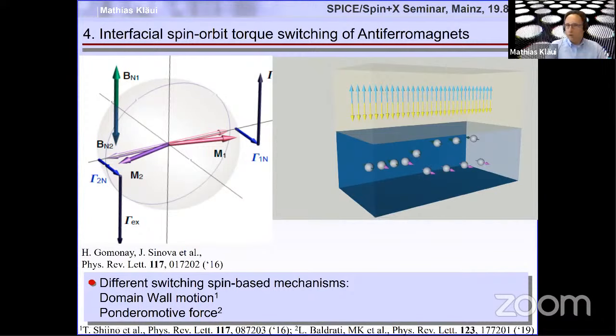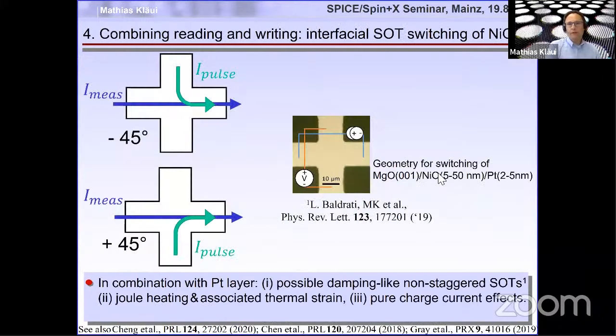So we set out to see if this can be seen in these insulating antiferromagnets with some heavy metal on top. And for that, we patterned nickel oxide films with some platinum on top on MgO, and injected current pulses along 90 degree different directions, as seen here and here. And then what do we expect? Well, possibly effects of these non-staggered, damping-like spin orbit torques, possibly Joule heating and associated thermal strain, and possibly pure charge current effects in the platinum.